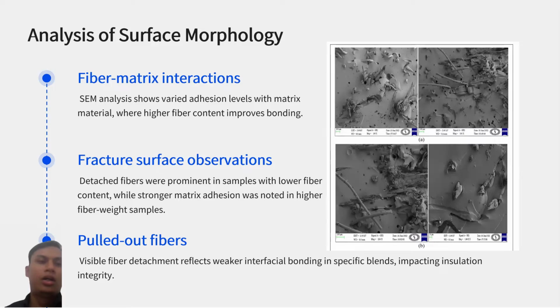Next, the analysis of surface morphology. We use SEM analysis showed varied adhesion level with matrix material, where higher fiber content improves bonding. Fracture surface observation. Detached fibers were prominent in samples with lower fiber content, while stronger matrix adhesion was seen in higher fiber weight samples. Pulled out of fibers. Visible fiber detachment reflects weaker interfacial bonding in specific blends, impacting insulation integrity.